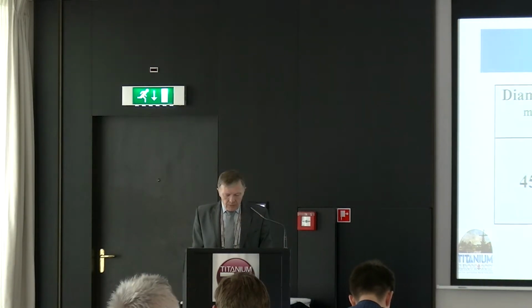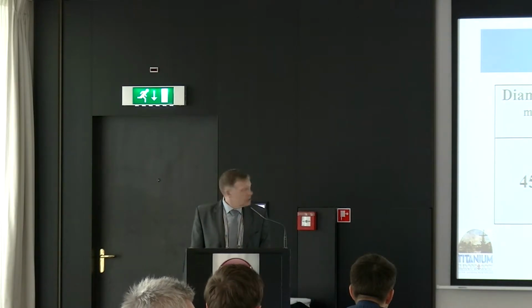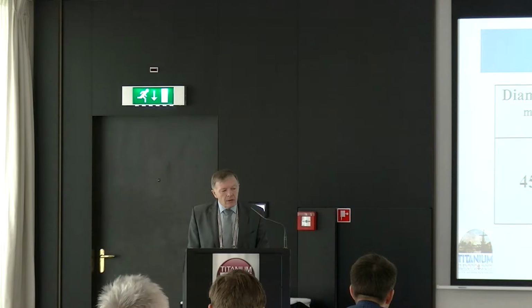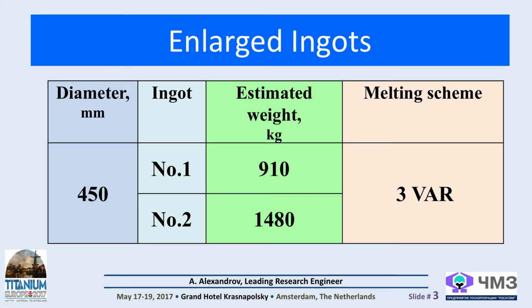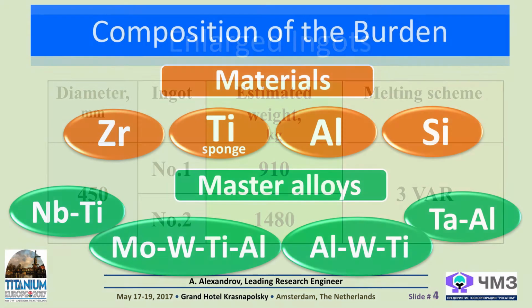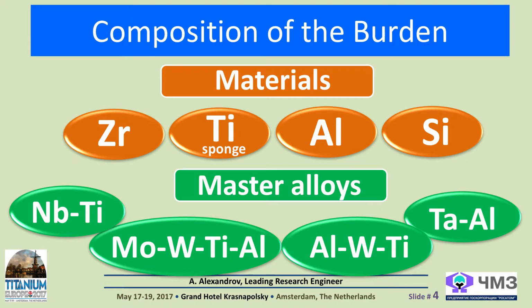In the course of the work, 2 enlarged industrial ingots of the VIT1 alloy with a diameter of 450 millimeters, of triple melting scheme, you see, triple vacuum arc remelting, with the estimated weight of 910 and 1480 kilograms, were obtained at the JSC ChMZ. The following materials were used for smelting ingots: titanium sponge, zirconium, aluminum, silicon, and complex master alloys: niobium-titanium of NT47 alloy, molybdenum-tungsten-titanium-aluminum, aluminum-tungsten-titanium, and tantalum-aluminum.